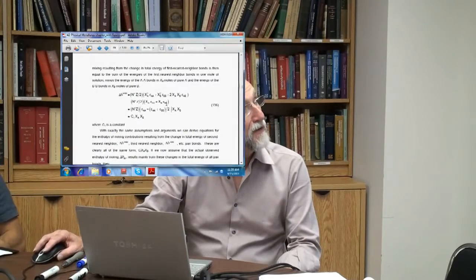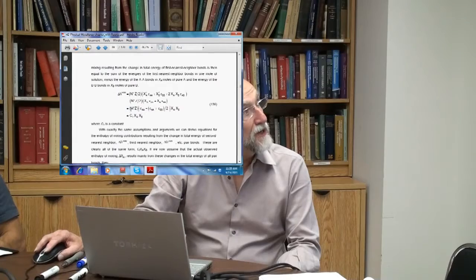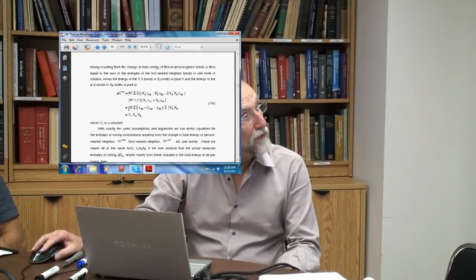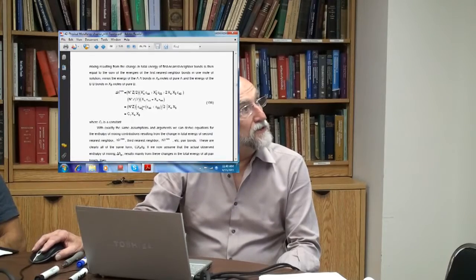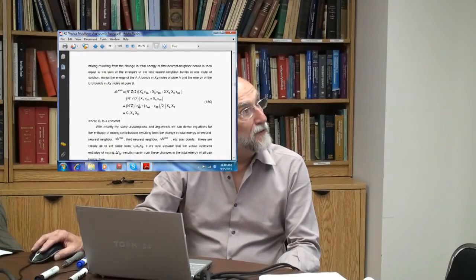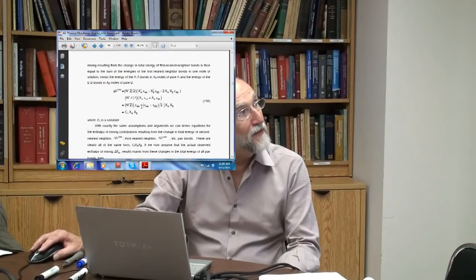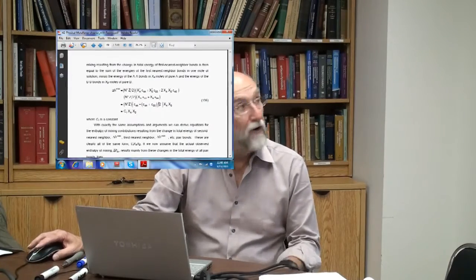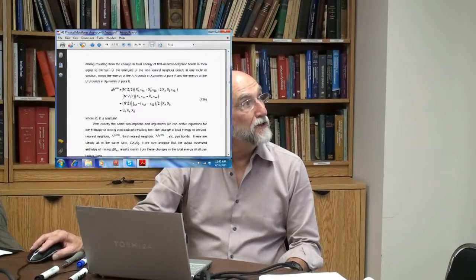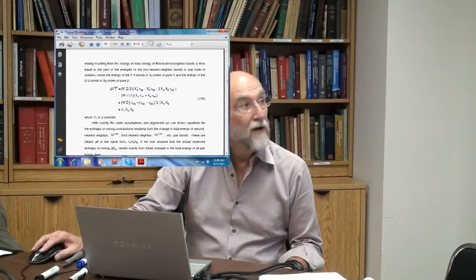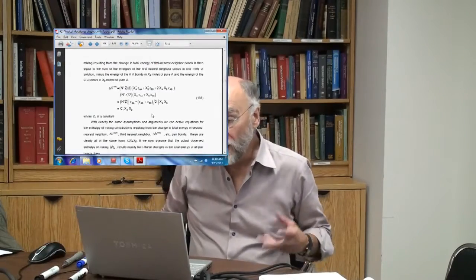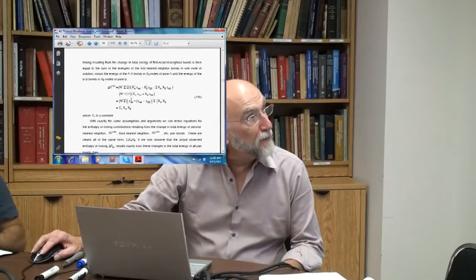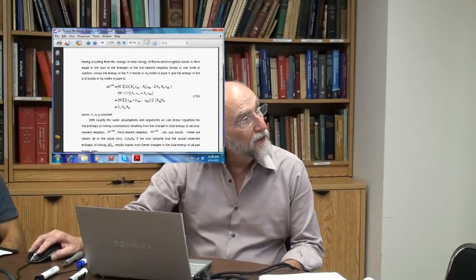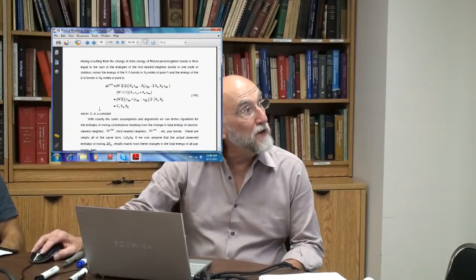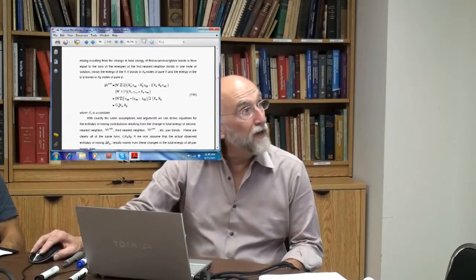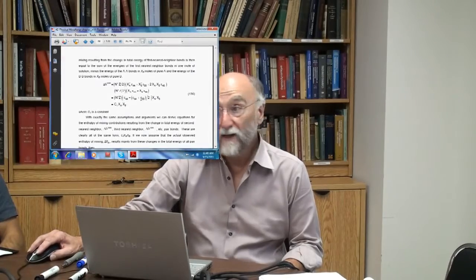So you can play around with this yourself and combine terms. So the constant then is N naught Z times all this. This C1 is this whole thing here, which we've assumed is constant. Now you can see that this term depends upon the difference in the energy of an AB bond and the average energy of the AA and BB bonds. If all the bonds have the same energy, then this term is 0 and delta H is 0. Suppose the AB bonds are stronger. Stronger bond means more negative energy. In that case, the epsilon AB is more negative than this here, and so this whole term becomes negative. And that gives you a negative contribution to delta H. C1 is negative if the AB bonds have a more negative energy than the AA and BB bonds.